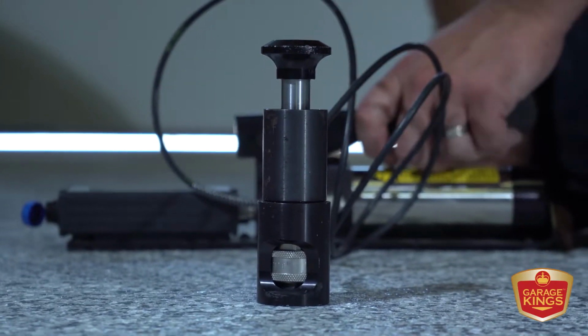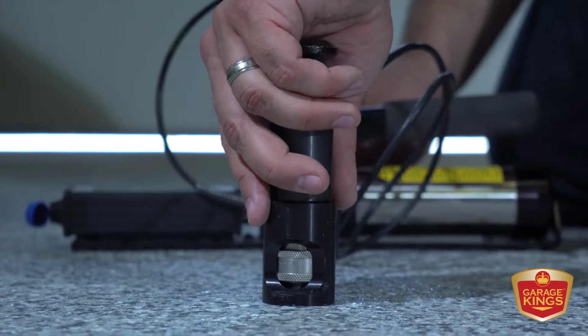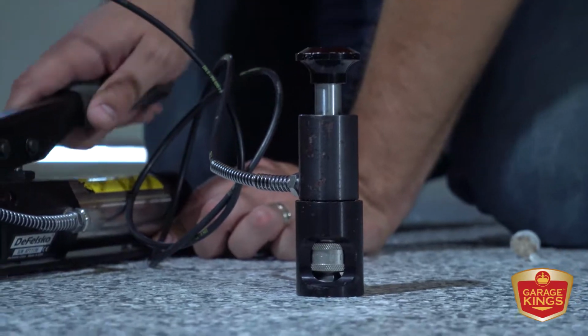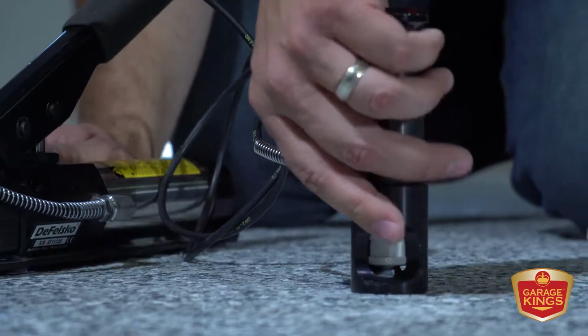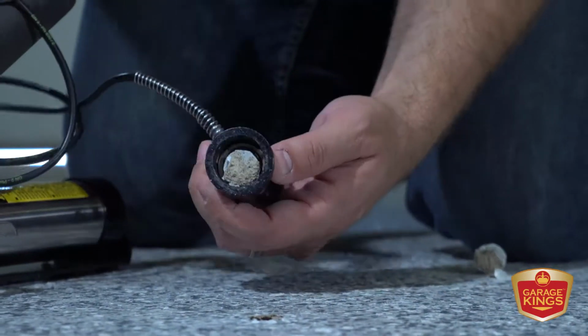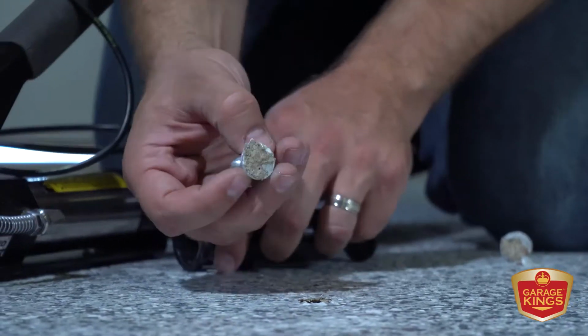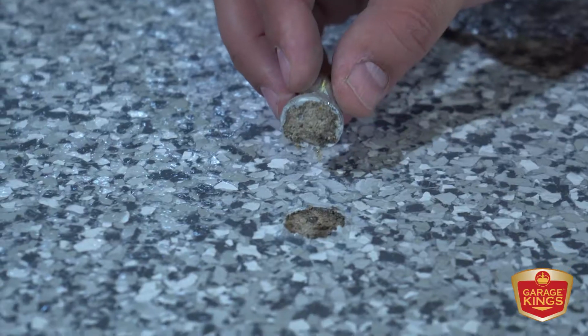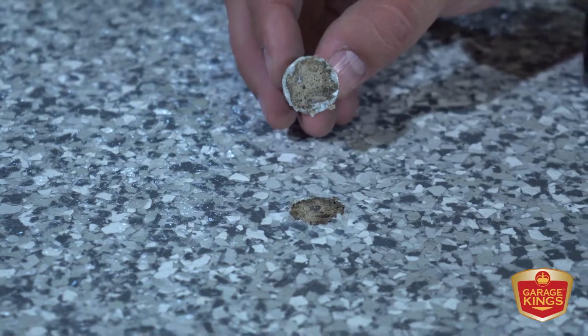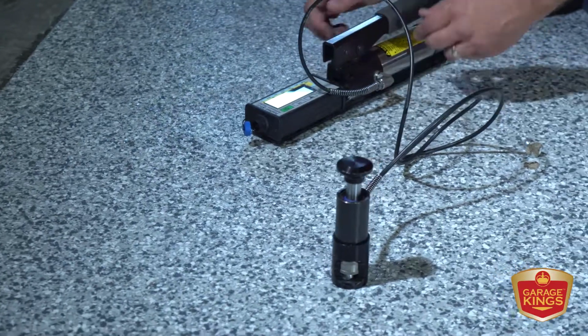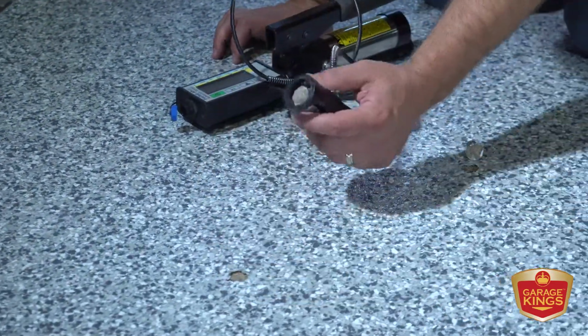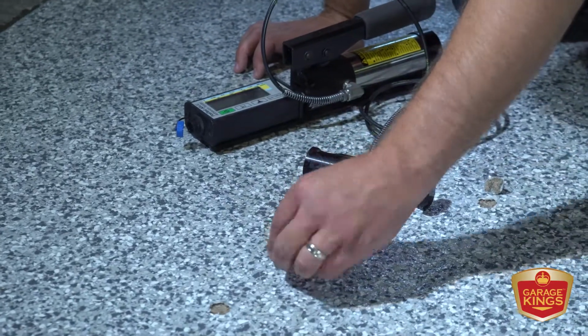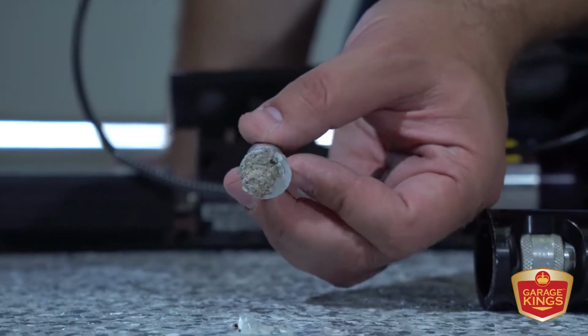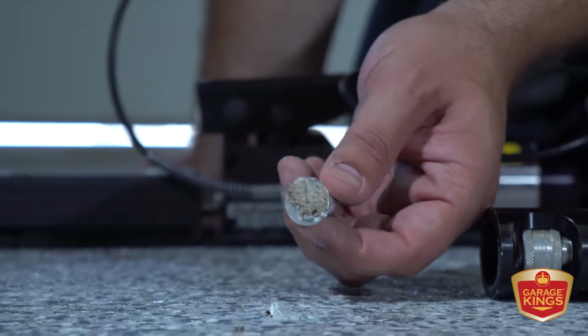And what we'll find is either coating delaminating from the concrete, which would be a bad thing. That's why we do all the surface prep and the grinding and create profiles so that the coating does not lift from the concrete. What we're looking for is for the concrete to actually fracture, and when this puck finally comes up, the coating will be there, but there will be concrete stuck to the bottom of that coating where the concrete actually fractured and broke, as opposed to the coating just lifting up from the concrete.